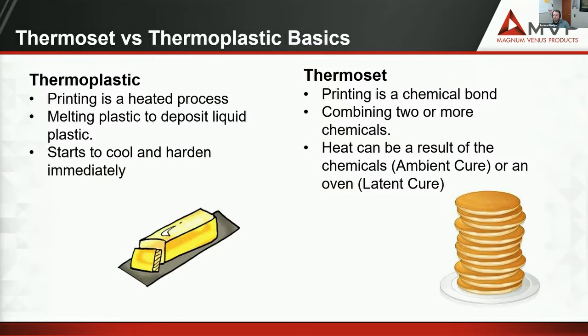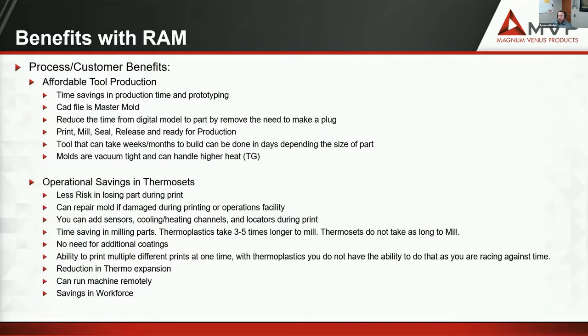With thermosets, the big difference is you're using two different materials that are cross-linking and meter mixing through a gun head and then deposited onto a table, and they're curing at ambient temperature. And when they're curing, they're actually building stability and stacking up, and everything's cross-linking together as we do these prints. I'm not going to go through the whole list here of the benefits we see with RAM, but it's about affordable tool production, and a lot of time savings with production and prototyping. A big thing that we like to say is your CAD file is your master mold. You don't really have to build a master mold if you don't need to.